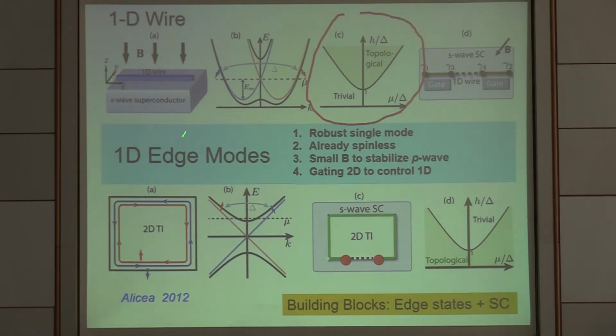So if we look at this view of the Majorana 1D edge states, there are two different platforms. One is the 1D wire, where you use those parameters: the Fermi energy or chemical potential, the energy gap of the superconductor, and also the Zeeman energy. You can tune these in the 1D case to turn it into the topological case, a P-wave one-dimensional wire. So you need a finite strength of magnetic field applied to the system. Now, if you don't apply magnetic field, you end up in the trivial state.